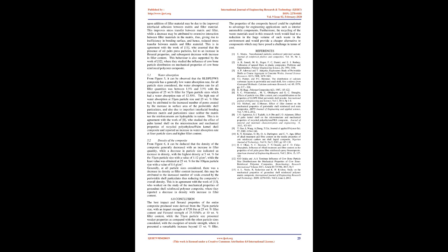6.0 Conclusion. The best impact and flexural properties of the entire composite produced were derived from the 75 µm particle size, with an impact strength of 1720 J/m at 25 weight% filler content and flexural strength of 25.51 MPa at 10 weight% filler content, while the 53 µm particle size presented weaker properties as compared with the other particle sizes considered, with the exception of tensile strength, where it presented a remarkable increase beyond 15 weight% filler.